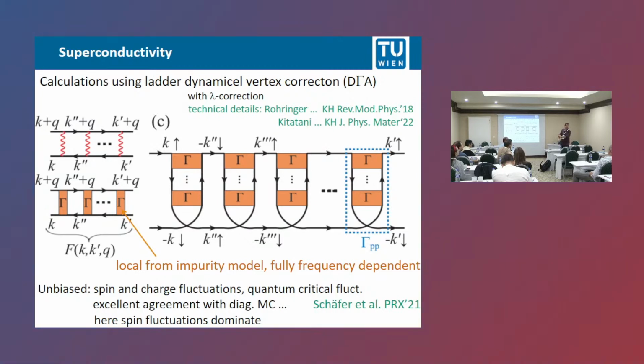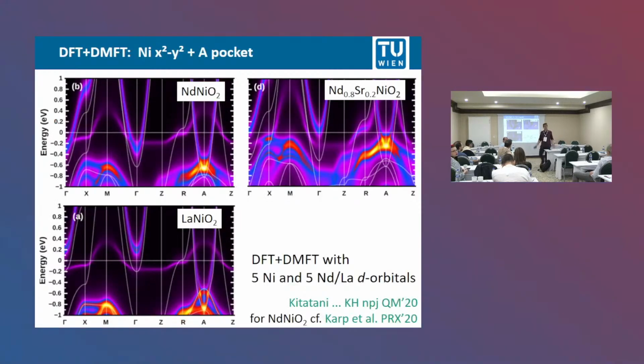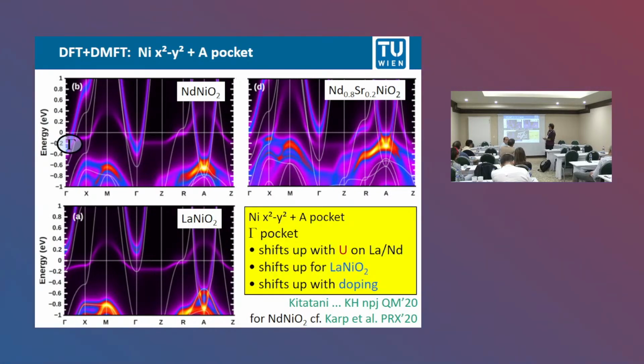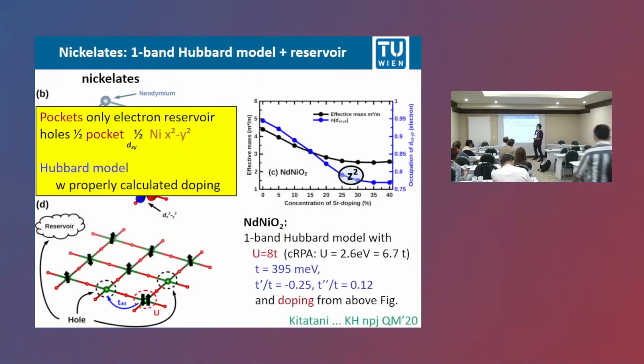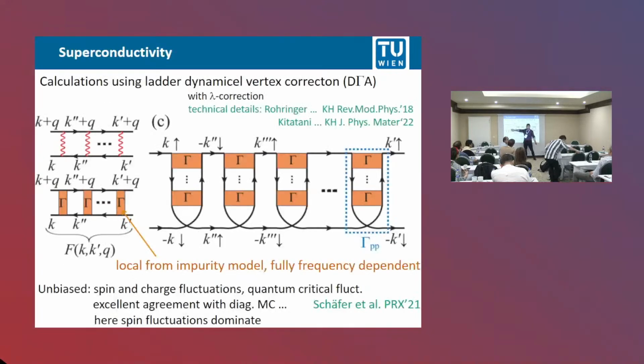And could you repeat the second question? DMFT, does it do something just to shift the pocket, or does it do something to the superconductivity? So DMFT has no D-wave superconductivity. To describe that, we have to go beyond DMFT. Walter is also an expert on that, so we have to use these extensions of DMFT. So from the DMFT calculation we just get the vertices, local vertices. If you connect these local vertices by local Green function, you get the DMFT self-energy. But if you do non-local Green functions, then we get antiferromagnetic spin fluctuations among others. And we see here these antiferromagnetic spin fluctuations dominate.